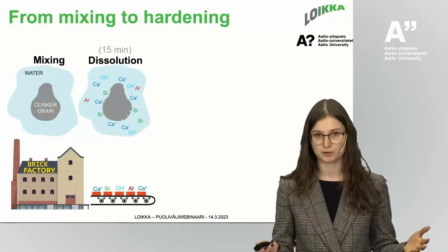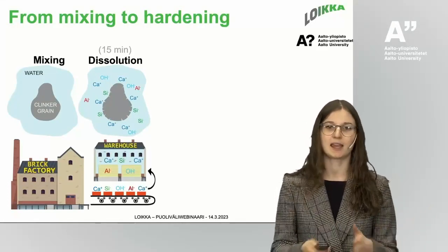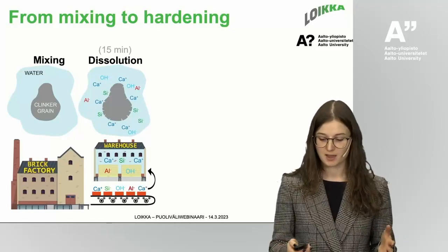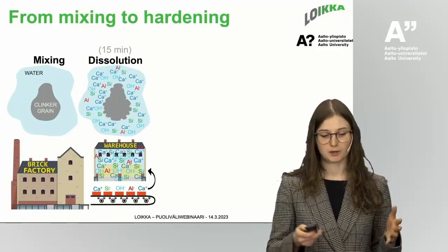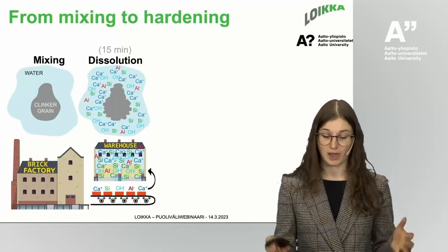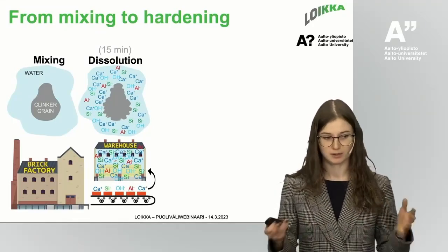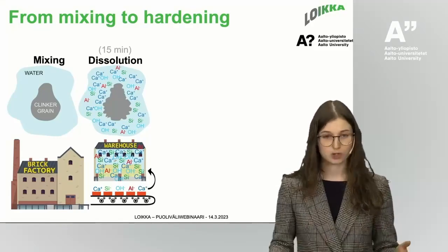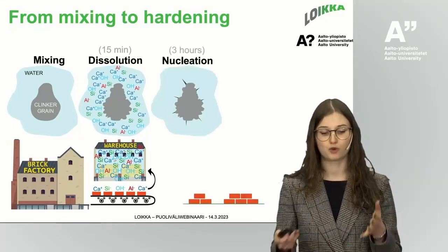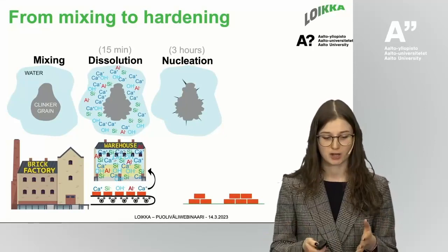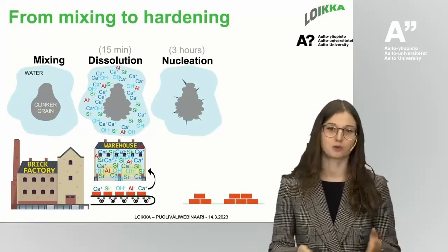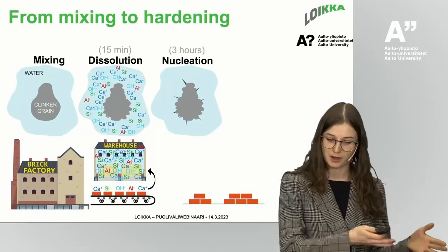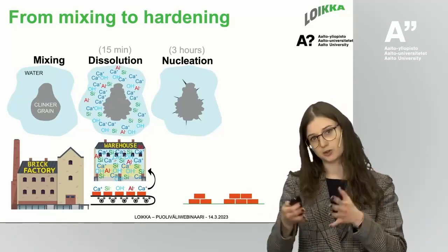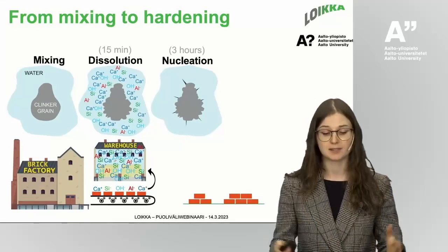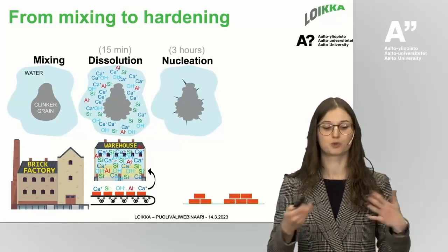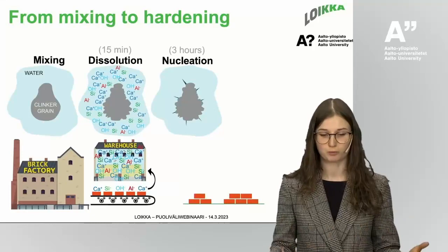So the brick factory is producing bricks, and the water is acting as a warehouse for all these ions. At the moment when we have so many ions in the water that the warehouse, which is the water, cannot accommodate any more, the hydrates start forming, and this process is called nucleation. This is the moment where you start building your brick wall. By removing some ions from the water into the hydrates, you have more space, and the clinker grain can dissolve more and produce more bricks.